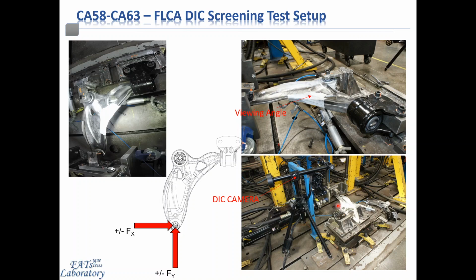Simply all we need to do is paint the surface with a speckle pattern, so you can see that illustrated here, and that was utilized in the critical region of the arm which we knew from finite element analysis, and we provided some margin of safety. So we're looking at a window of the surface, and it was observed using a stereo camera system shown on the bottom left here, while the fatigue test was running. So under the peak tensile load reversal, we would capture images. This technique proved to be very successful in understanding the nature of the fatigue failure due to forging defects within the components which were manufactured.